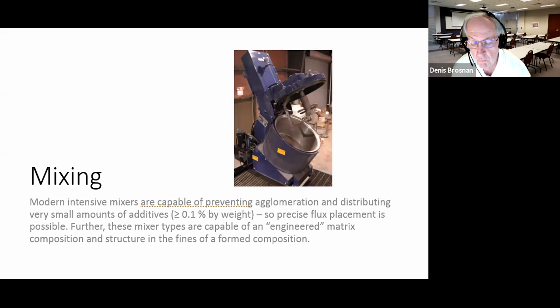So this is a picture of the intensive mixer in my laboratory. You can see that there's a rotating pan where the material is charged into, and there is a high-speed agitator that is inserted into the material that lifts the material and knocks it around and helps distribute that liquid. So this is an intensive mixer. If you have such a mixer like this, you can do wonderful things with a microstructure. If you have an inefficient mixer, you probably can't.